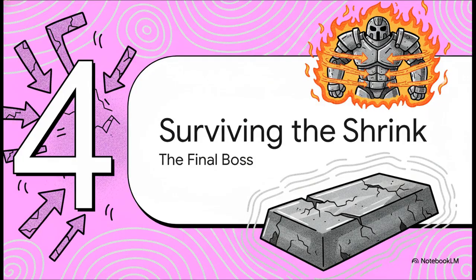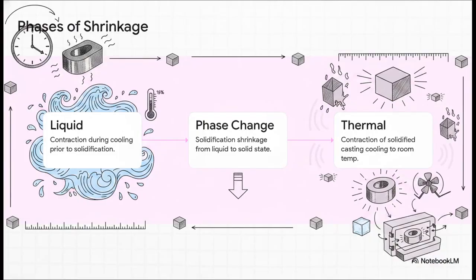Okay, finally, Section 4, Surviving the Shrink, the final boss. So why does the metal shrink so aggressively in the first place? Well, it's an inevitable physical reality, and a cast part has to survive 3 distinct phases of it, chronologically. First up is liquid contraction, which happens as the superheat bleeds off just prior to freezing. Then you have solidification shrinkage. That's a sudden, pretty significant contraction right during the actual phase change from liquid to solid.